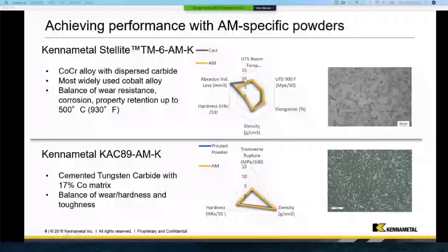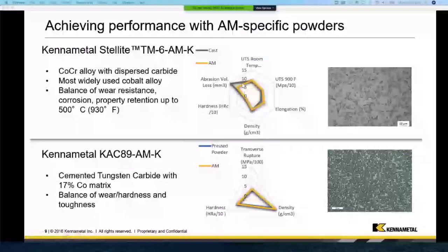I show a little spider diagram here. I had to normalize these so I could fit everything on at the different scales. But what it basically shows is that when we compare what we can get with additive manufacturing to an investment cast Stellite 6, we are basically overlaying with the same properties in ultimate tensile and tensile at temperature, elongation, yield, density, hardness. And we actually have, in volume loss, a little bit less volume loss in the additive. They're also very analogous to what you would typically see in a cast structure with Stellite 6.